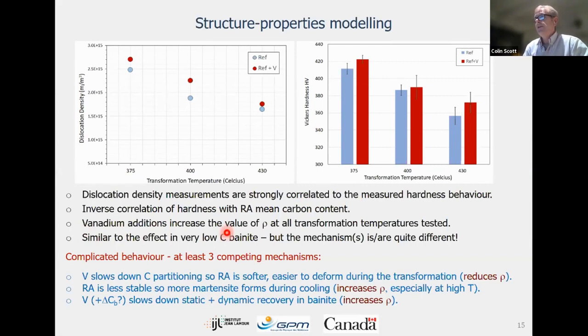So we have a very complicated behavior. There's at least 3 competing mechanisms involved. So what we see is that vanadium slows down the carbon partition to retained austenite. So the retained austenite is softer.